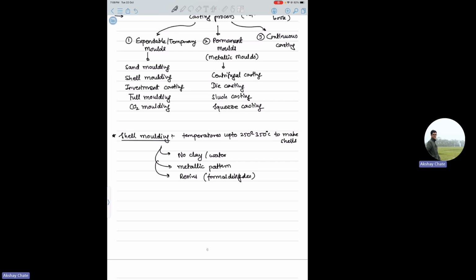Okay. The thickness of these shells depends on how much time you give, which is called dwell time. The shell thickness is proportional to the square root of time, the dwell time. So the longer you keep the shell on the metallic pattern, the thicker it will grow, but it's not a linear variation with time. It's a square root variation. Okay.